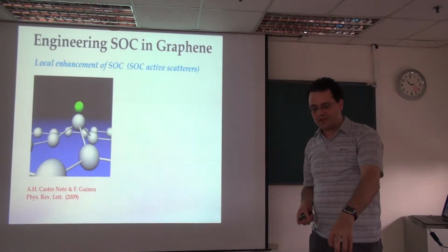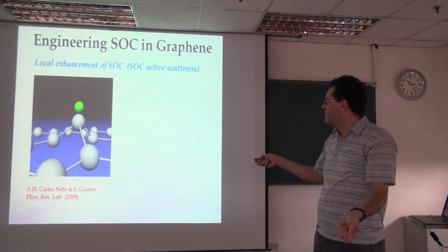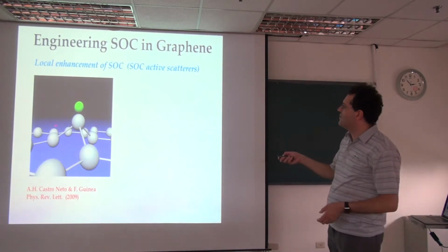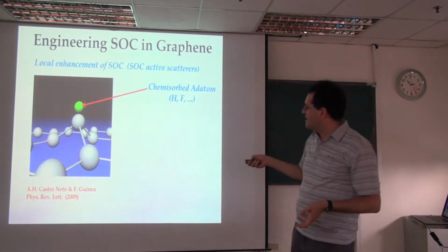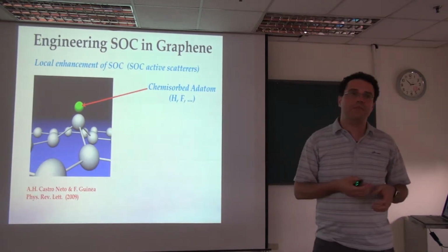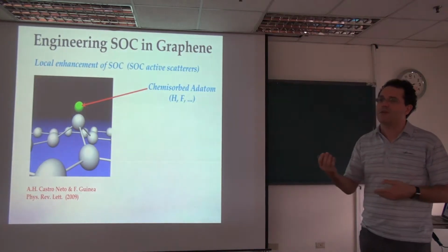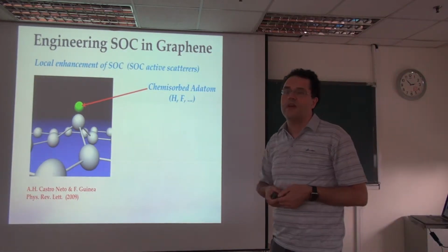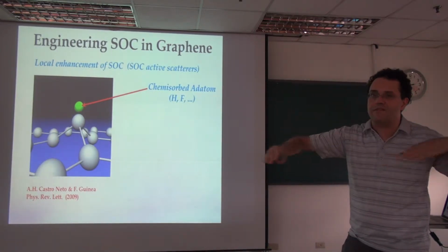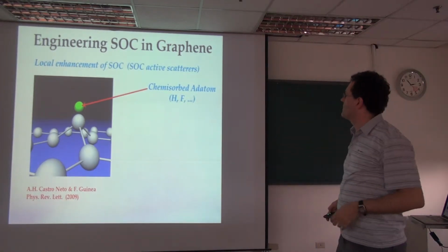As a consequence, it will pull this carbon atom out of the graphene plane, so it will induce a local deformation. Now, local deformation in graphene, this deviation from planarity, happens through what the chemists call sp2, sp3 hybridization, which is essentially a different combination of s and p orbitals from the one that exists in perfectly flat graphene, which is symmetric under mirror symmetry.